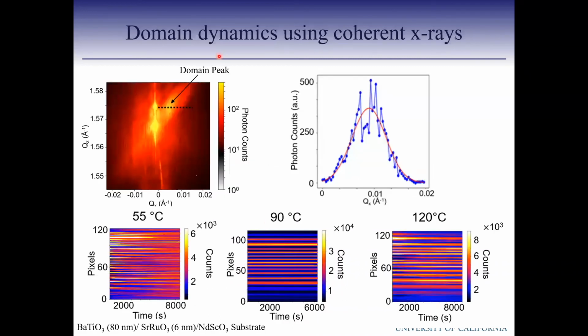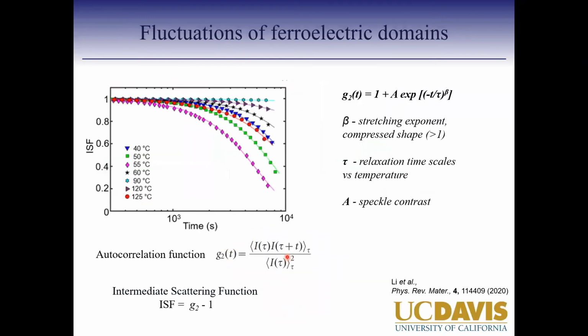So we can collect this image as a function of time, and we can correlate it with itself and then plot that autocorrelation function with itself. And that is directly related to how the intermediate scattering function, which is the dynamic structure factor of the material, evolves. So I can plot the dynamic structure factor as a function of time, and fit this with an exponential format, exp[-(t/tau)^beta], and can get the tau, which is the critical time scale of these fluctuations for each temperature.